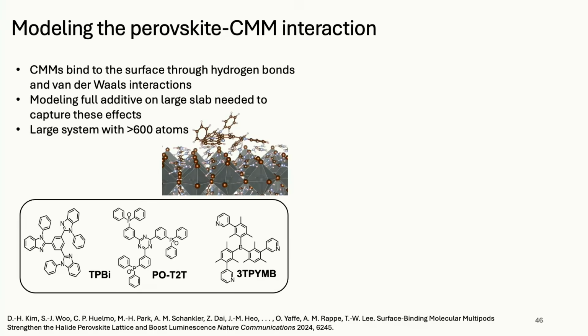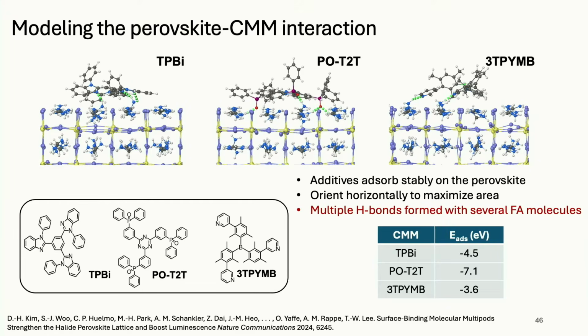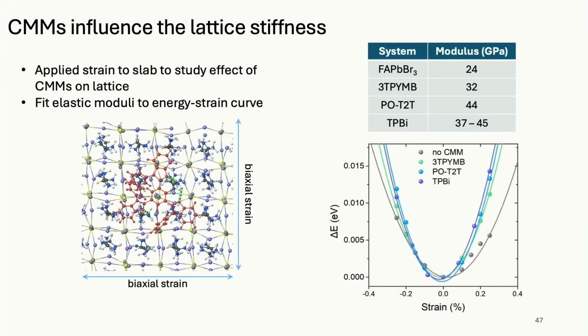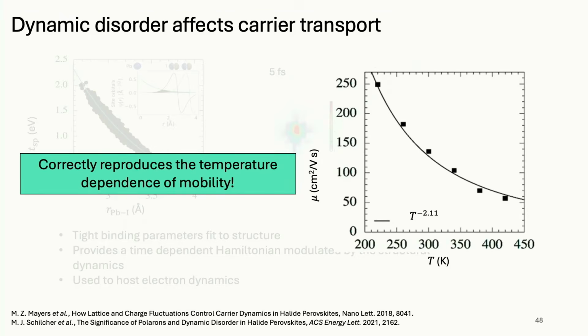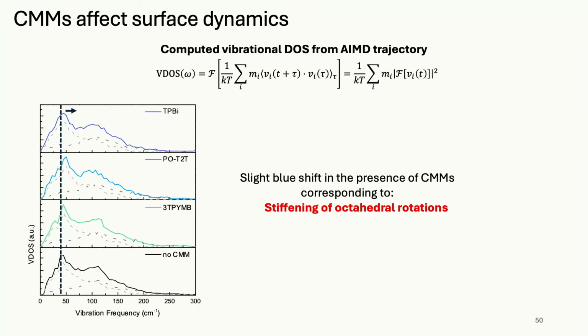So that's pretty neat. But what we did that's even more direct, we got one of my friends, Omer Yaffe, involved, who is great at taking Raman spectra. So we calculated the Raman spectrum without any additives, and the peak is here, like at 40. But then if you add any of these additives, the peak shifts. It's not a huge shift, but it goes to like 60 or 55. And so you're taking the low frequency modes and you're hardening them. So it will have smaller amplitude, higher frequency motion. This moves you in the direction of less electron hole scattering, less keeping them apart, faster recombination, higher efficiency.